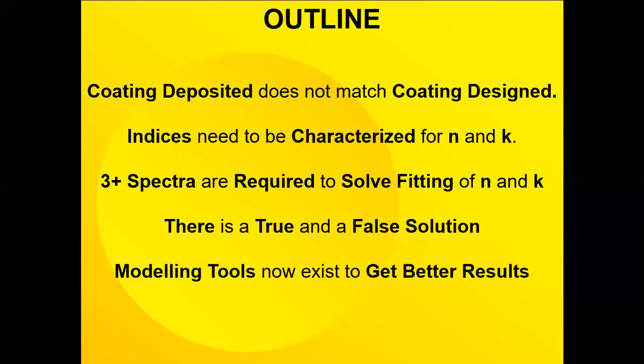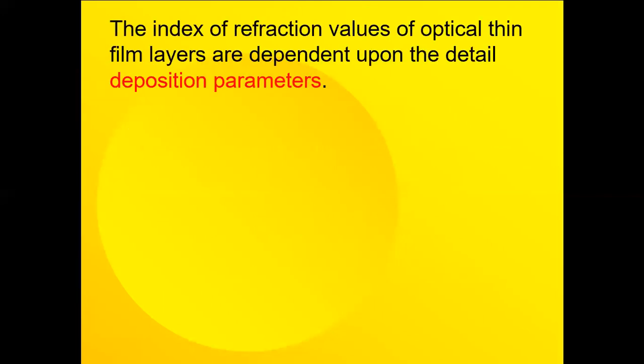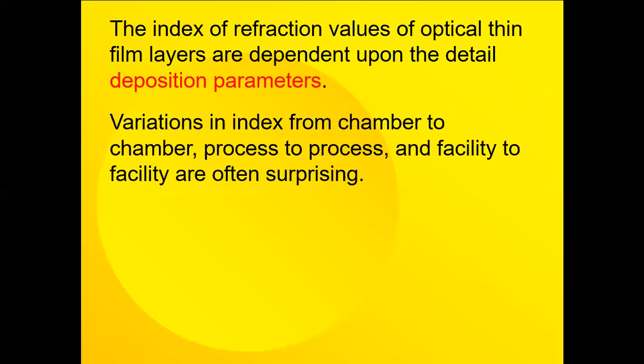The modeling tools now exist to get better results than previously available. The index of refraction values of optical thin film layers are dependent upon the details of deposition, so we can get significant variations. Variations in the index from chamber to chamber and process to process and facility to facility are often surprisingly different.